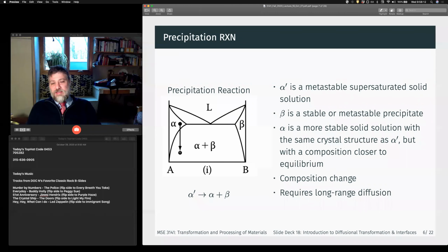The other thing to realize is that we're going to have a composition change everywhere, right? Because the alpha that remains is going to be over here, and we have beta over here. And this precipitation, the growth of beta from this alpha, requires long-range diffusion. It requires moving B out of the alpha and into the beta precipitates, right? So because this requires long-range diffusion, we can quench it out. We can get the microstructure we want and quench down and maintain it metastably, right? So precipitation is the first one.